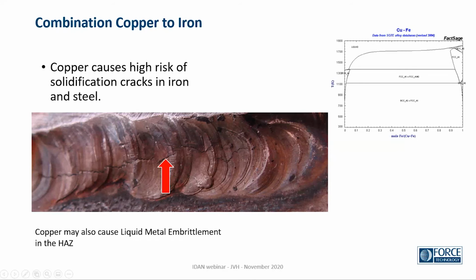We also have copper to iron, which is giving problems with solidification cracking. In this example, we have a crack along the center of the weld. Some of you might recognize it as similar to hot cracks that we see when the surfaces are contaminated or the material is high in sulfur. Here we have made a similar crack by increasing the copper content.